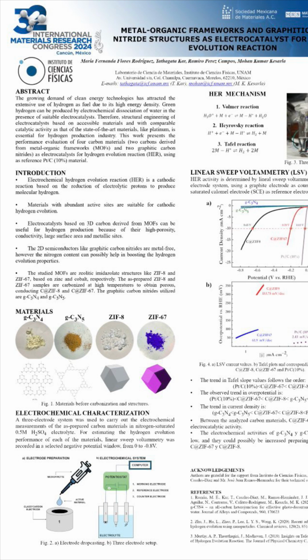molecular hydrogen. However, the use of expensive noble metals as electrocatalysts for generating hydrogen from electrochemical reactions has limited the commercial production. Therefore, synthesis of low-cost electrocatalysts with high catalytic activity and good performance stability has become an important research topic. For this work, we tested 4 materials, 2 graphitic carbon nitrides and 2 metal-organic frameworks to evaluate their performance for hydrogen evolution reaction. Because of its porosity, these materials have abundant active sites, which may favor the reaction.